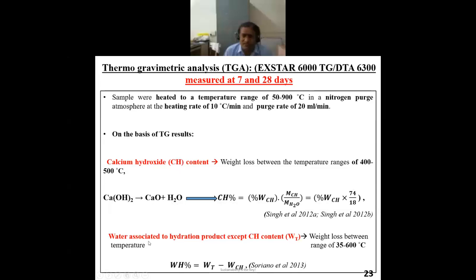Then the water associated with hydration products except the CH. Now remember, this is nothing but your calcium silicate hydrate. We cannot say it is exactly calcium silicate hydrate, but it resembles calcium silicate hydrate. The weight loss, remember, happens between 35 to 600 centigrade. Here, calcium hydroxide is between 400 to 500 centigrade. That is more important actually. I will tell you from the graphs how we determine it. This is the formula given by one of the researchers, and by adapting this, we can determine the water associated with the hydration product except the calcium hydroxide.